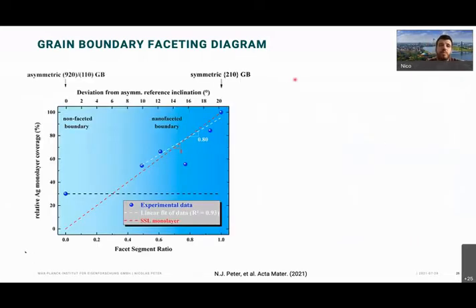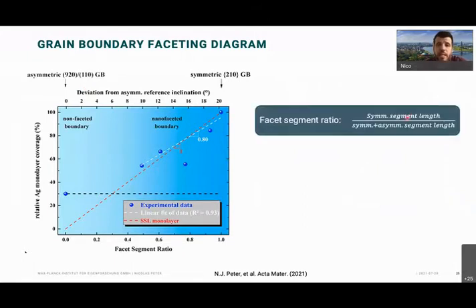From this, we were able to construct this diagram here, and this gives now the facet segment ratio, and this is basically the symmetric segment length. So how long is a segment of the symmetric silver containing stuff in relation to the entire facet. And this is what we plot here against the coverage again, so the concentration if you want.